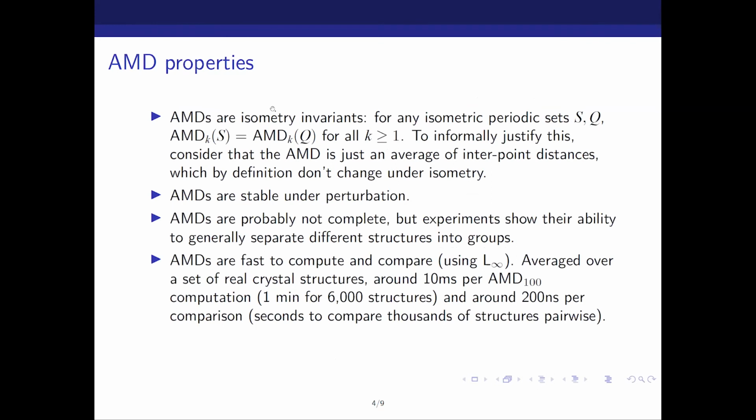And we're just going to quickly run through the properties of it to show that it kind of ticks boxes we might want it to tick. So first of all, they are isometry invariants, and they're continuous, which is, I mean, it'd be pretty bad if it wasn't, since we set up the motivation as such. Unfortunately, with regards to completeness, we think they're not complete. It's actually relatively difficult to confidently decide that one way or the other, but we're pretty sure they're not complete. Not that it necessarily matters, because you can have continuous isometry invariants that are not complete, but very useful, like density, for example.